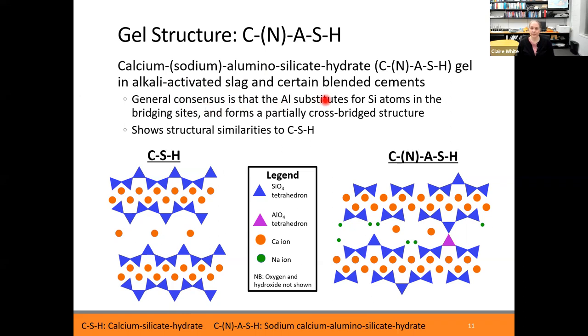We know that aluminium substitutes for silicon atoms in what's known as these bridging sites, which, for example, is shown here. It bridges across the interlayer region, the hydrated region. And we know that the system has structural similarities to CSH gel. We know that there's these silicate, aluminosilicate chains that exist. They have finite length. The stuff that we don't know so well is what sodium does to the system. And so that's what I'm going to concentrate on today, is can we understand the impact of sodium on the structure of the gel? And can we understand the impact of sodium on the thermodynamics of the gel as well?